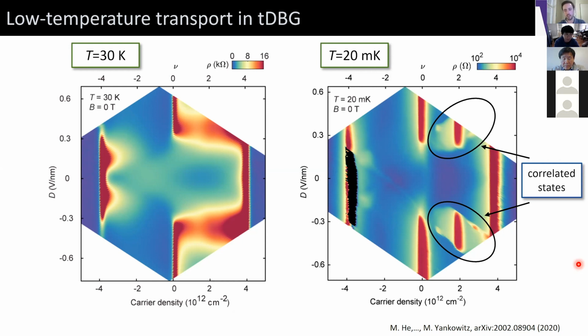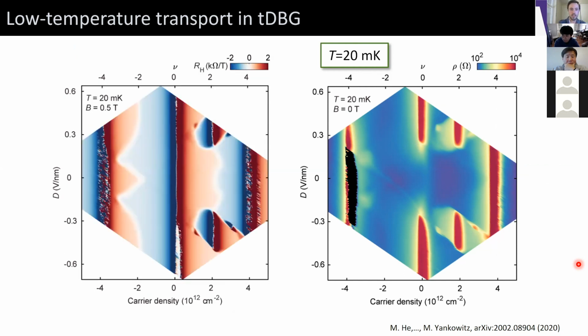Okay, and because we can't understand these from the single particle model, we don't anticipate insulating states at partial band filling. We attribute them to consequences of correlations within the flat conduction band. We can get a bit better of a handle on what's going on by also considering the Hall resistivity.